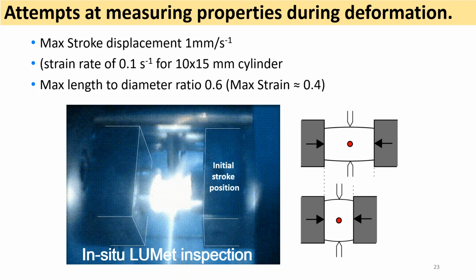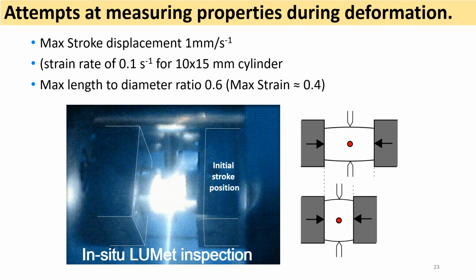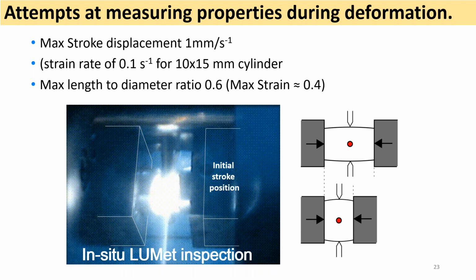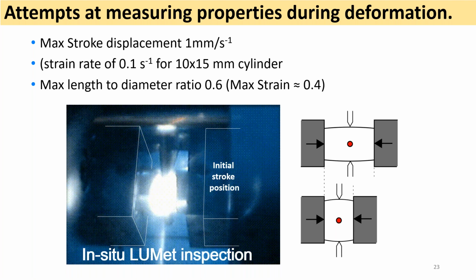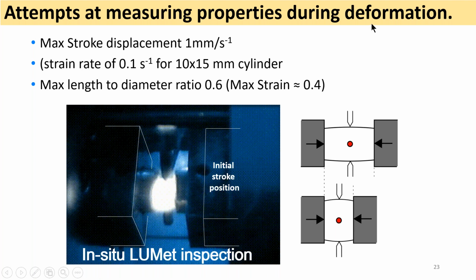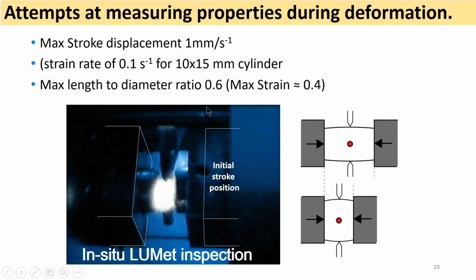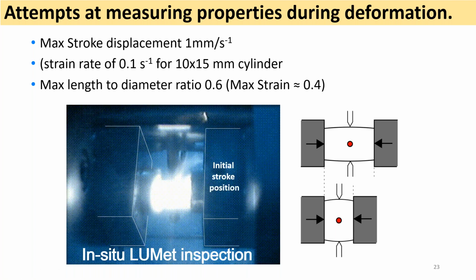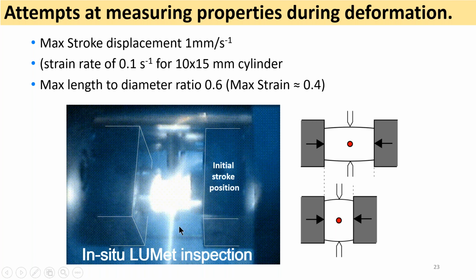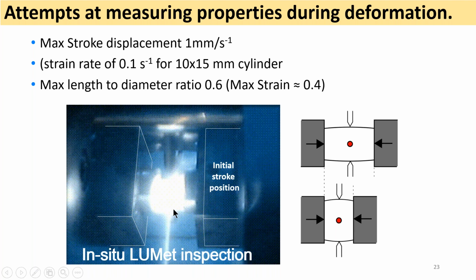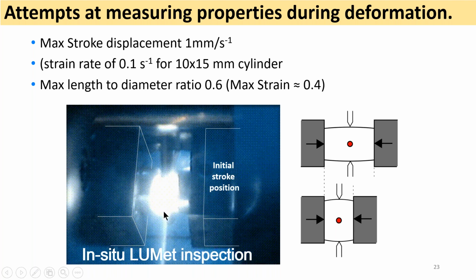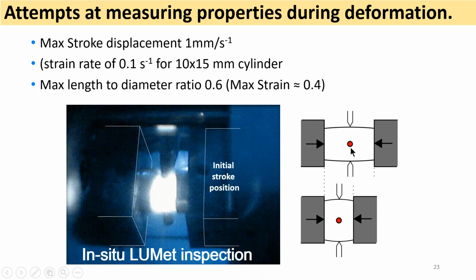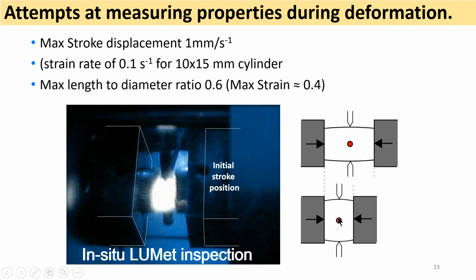So now, of course, we were always interested in trying to measure during the deformation. I've taken three slides to illustrate what can be done, but I've written that it's an attempt at measuring property during deformation, because work still needs to be done in order to publish those results and reassure ourselves that measurements are possible during the deformation. The Lumet features a system which can move the laser simultaneously with the stroke of the Gleeble machine. That's an important feature to ensure that the measurement remains at the center of the sample, in which the strain is captured.